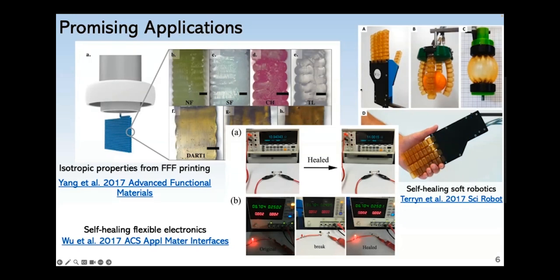And then in this last set of images in the top right are shown some robotic grippers out of DA material. And so a few of the major challenges with bringing robotics into our everyday lives is having differential grip strength and the wear and tear of many jointed parts like these hands or grippers. And the differential grip strength is important so that the gripper can apply the right amount of pressure to pick up different soft or hard objects. And ideally, these need to have a long service life. These researchers were able to show that some DA chemistries are good candidates to help tackle both of those issues due to their soft and self-healing qualities.